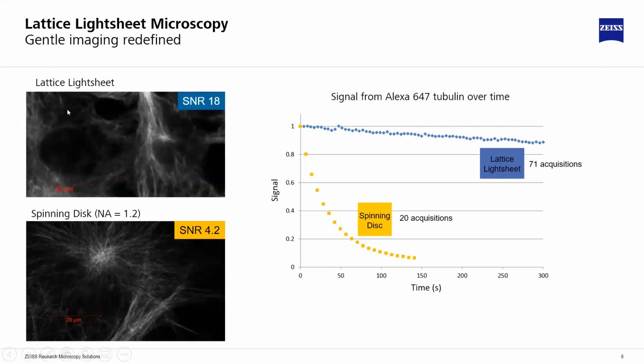And you can really see the benefits of gentle imaging, for example, with a lattice light sheet quantified here in this graph. So here on a spinning disk confocal, the fluorescence signal is almost entirely lost after 150 seconds of continuous imaging time and 20 acquisitions. However, in comparison, on the right side here, we see the lattice light sheet. These same samples display a minimal decrease in fluorescence intensity. And this is after almost 300 seconds of acquisition and 3.5 times more acquisitions of the same volume size. So this is 71 volumes over twice as much time, and we're seeing maybe 10% signal loss compared to 90 to 95% signal loss on a spinning disk confocal.